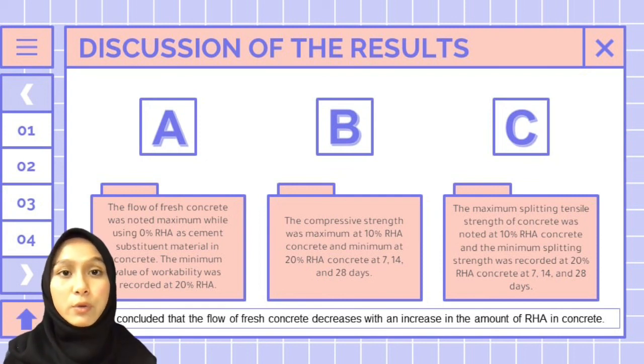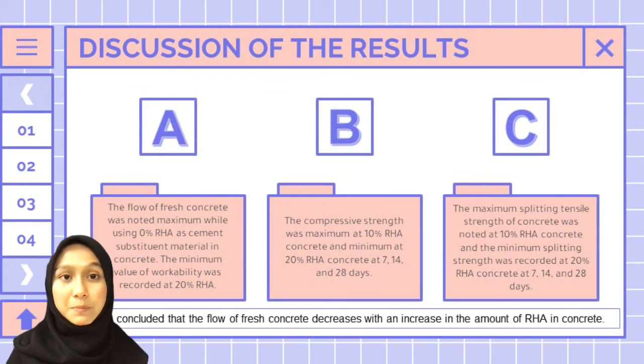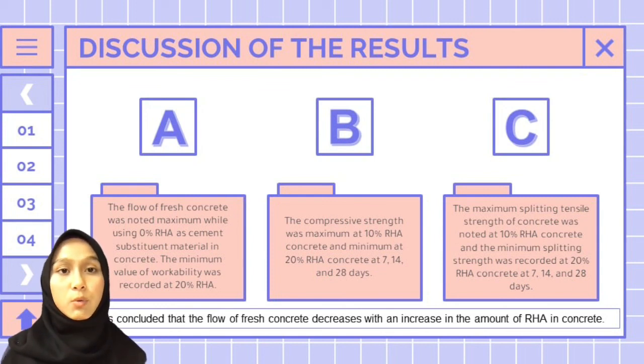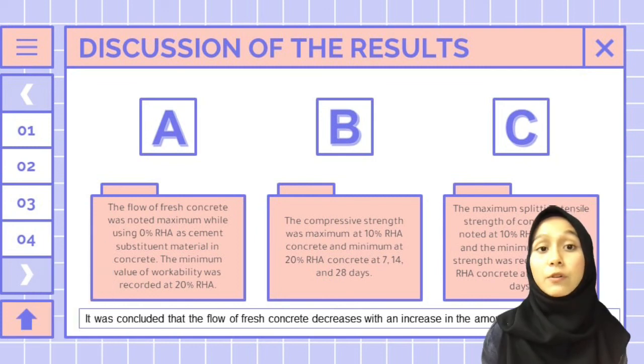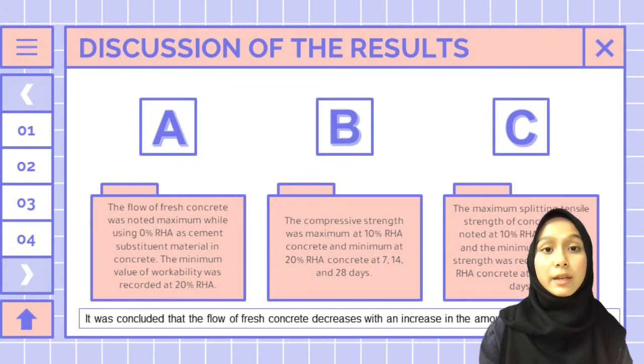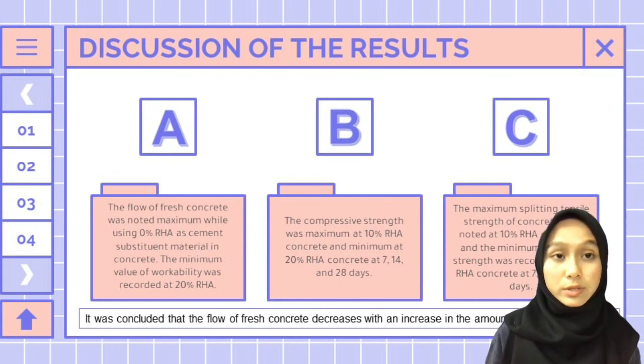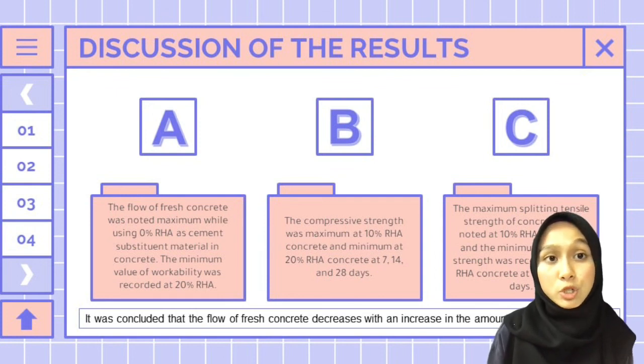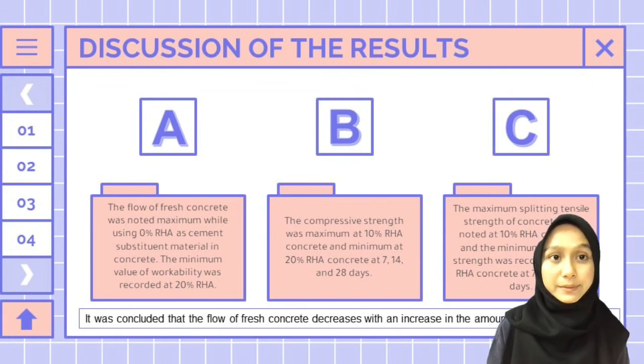And what we can conclude for the last test, test C, is the maximum splitting tensile strength of concrete was noted at 10% RHA concrete and the minimum splitting tensile strength was recorded at the 20% RHA concrete at 7, 14 and 28 days. From the article that I have described, it shows that RHA is suitable as a replacement of cement for the future sustainable concrete. It also shows that the RHA can reduce the cost, waste and pollution in concrete making.